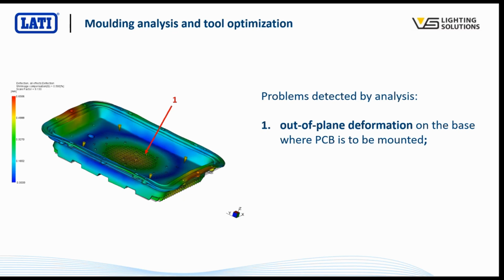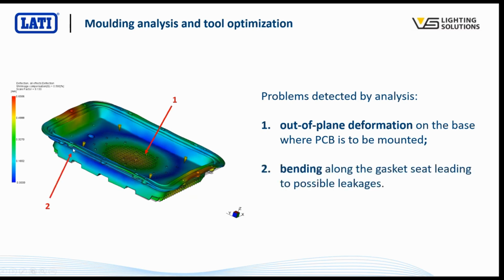Issue number one, and exactly the issue that we don't want, is some out of plane deformation on the base where the PCB and where the LEDs are going to be mounted. So as we've talked about, very bad news for maintaining good thermal contact. So that's something that needs to be mitigated. And the other thing that we noticed, you can maybe just pick it up on this drawing here, is a bit of deformation around the rim of the part here. And this is bad because this is exactly where the gasket would sit. That gives us the IP rating and keeps the moisture and dirt out from the electronics. So we need to mitigate this deformation here as well.